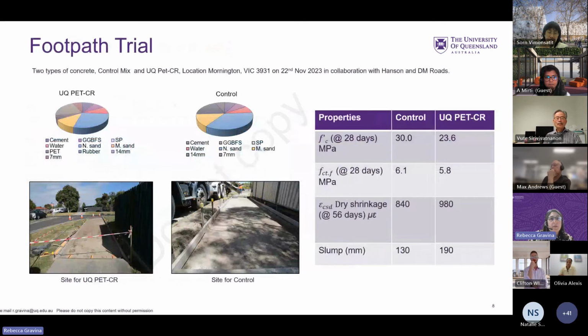Having done the LCA model, we chose the concrete mix design that has a combination of PET plastic and crumb rubber combined to replace our natural aggregate. So we've got a 40% replacement of the natural aggregate within the concrete mix design. We worked with Hanson and the local council, Mornington Peninsula Shire, and DM Roads to identify a site and carry out our field trial.